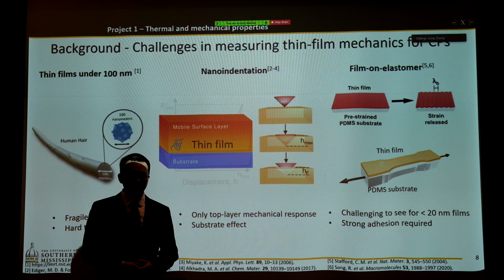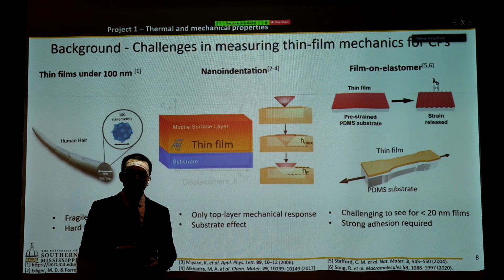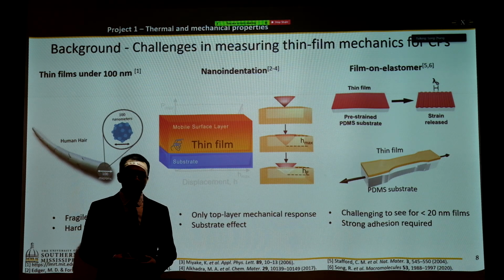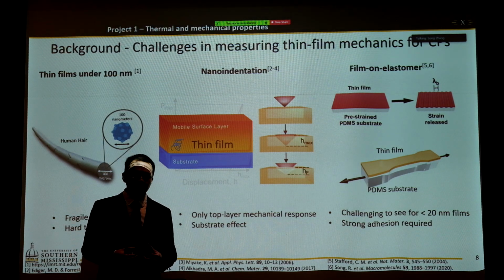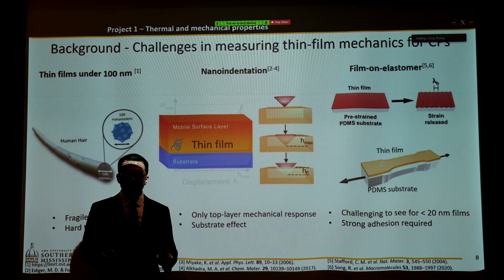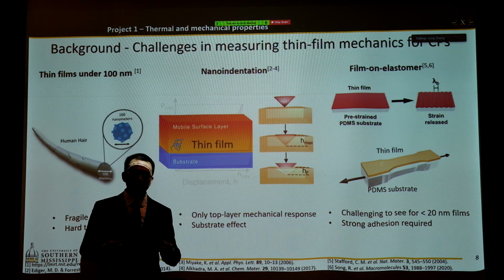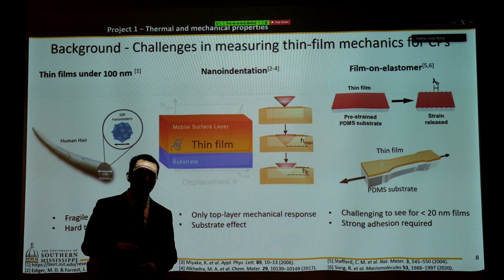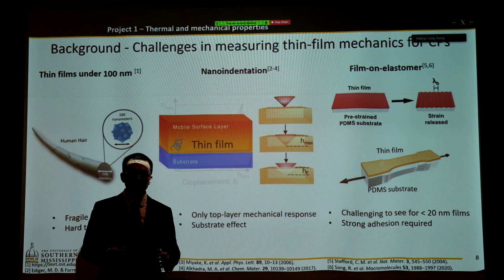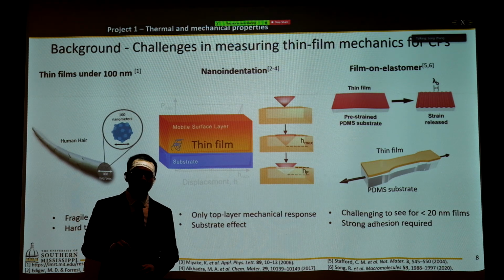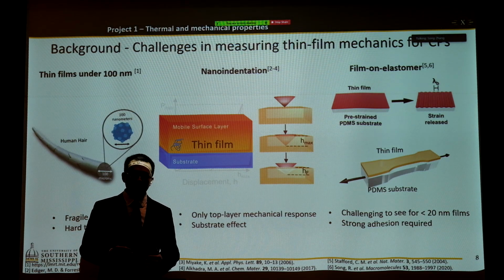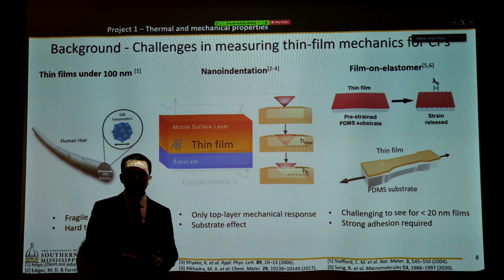The next technique is well applied in the literature. It's called the film on elastomer method. Now, if you want to understand elastic modulus, you simply stretch your PDMS substrate, then transfer the thin film on top of the substrate. Once you release that strain, you have a periodic buckling phenomenon on top of the thin film. And the wavelength of the wrinkling is directly correlated with the elastic modulus of your film.